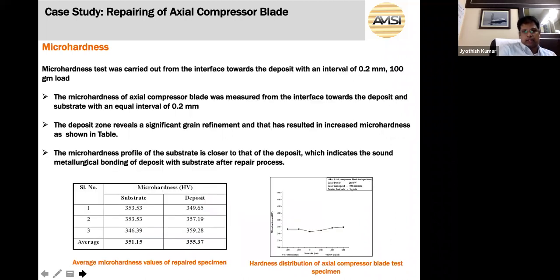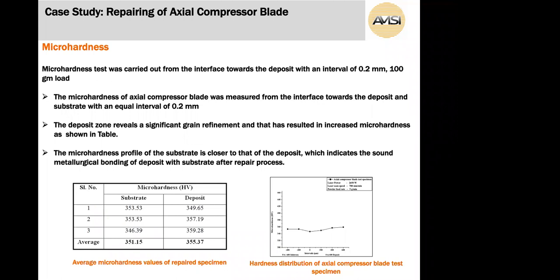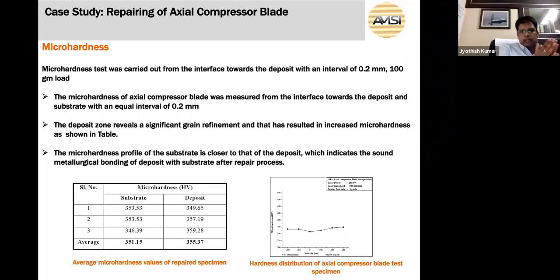Yeah. Also, we studied the micro hardness. The micro hardness is a very important factor. Once we deposit any material on the base material, we have to test the hardness. As you can see in the table, the deposited material and the substrate show almost the same values in terms of micro hardness distribution, which shows that the deposited material has bonded completely with the base material.